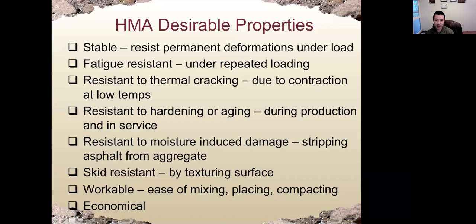Also resistance to moisture-induced damage. We call that stripping, stripping of asphalt from the aggregate. This is kind of similar to debonding of the Portland cement paste from the aggregate. And also skid resistance. We check the surface texture of the asphalt pavement. Also workability. Workability here means how easily we can mix asphalt binder with the aggregate, and how easily we can place and compact the asphalt concrete. This is similar to the slump test for Portland cement concrete. And also the cost of the materials.